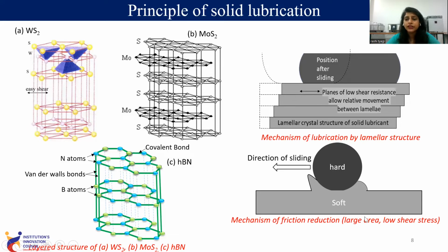As you can see in this figure, there is a large area, so there will be low shear stress, because shear stress is equal to force per unit area. These laminae align themselves in the direction of motion, so the area becomes large, then shear stress becomes small. So there is a low shear stress, and they can provide a low friction coefficient.